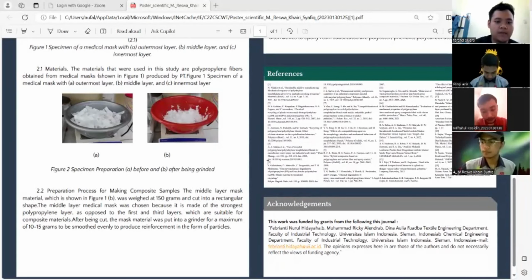2.2 Preparation process for making composite samples. The middle layer mesh material, which is shown in Figure 1b, was weighed at 150 grams and cut into a rectangular shape. The middle layer mesh was chosen because it is made of the strongest polypropylene layer, as opposed to the first and third layers, which are suitable for composite material. After being cut, the mask material was put into a grinder for a maximum of 10 to 15 grams to be smoothed evenly to produce reinforcement in the form of particles.